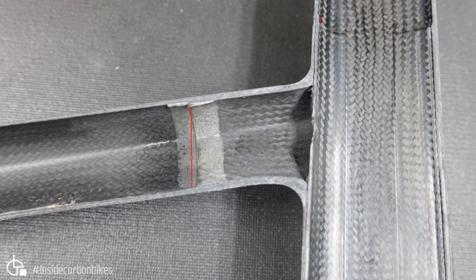You do see there's a crack indication through here, and also the corresponding lower junction, as was noted in the seat stay to seat tube junction. I'm not sure if that flexed open during the cutting process, because as a complete closed structure, when it's a complete bike, the loads on that would be contained much better. So the only way you could really get a crack propagating up like that is if you crashed the bike heavily, or if you had the bike on the roof racks and you drove into the garage and it impacted the top of the seat tube, so you had a real force going that way at the top of the seat, which could then propagate through there.